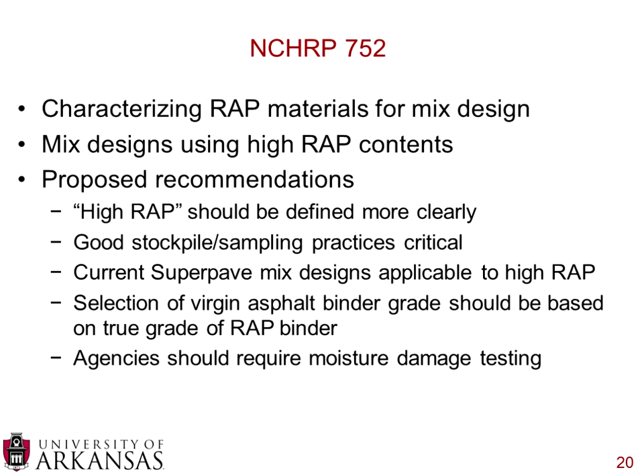They also believe that the selection of the virgin asphalt binder grade should be based on the true grade of the RAP binder. So they recommend that you take the extracted RAP material, extracted asphalt cement from the RAP, and actually run a PG binder grading regime on that in order to understand the exact grade that you have from the RAP binder. And then also they believe that agencies should require moisture damage testing.